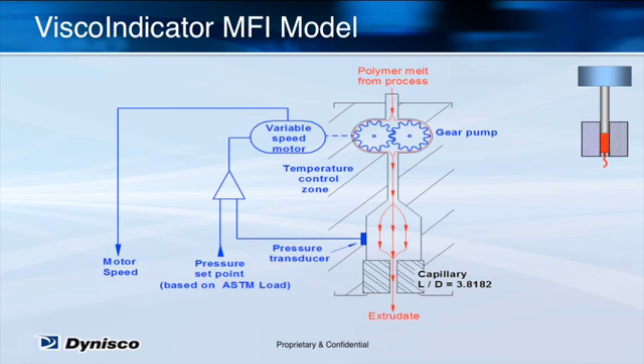A single pressure transducer is located above the capillary to measure driving pressure. The test polymer extrudes to atmosphere. By that I mean it falls to the floor, just like it would in a melt flow indexer. All material that enters the rheometer flows out as scrap, typically at the rate of 1/2 kilogram per hour. This rheometer duplicates the internal geometry of the melt flow indexer, so the capillary entrance effects are similar.